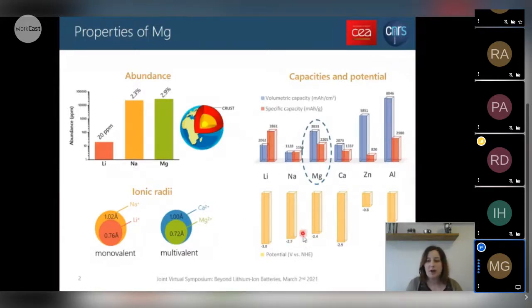Despite a smaller potential of minus 2.4 volts compared to minus 3.0 volts for lithium, magnesium is a great alternative to lithium, as it can exchange 2 electrons instead of 1 for lithium. The main advantage of magnesium is its high abundance in the Earth's crust, which, similar to sodium, could limit the cost of these batteries in comparison to lithium-ion batteries. Magnesium actually presents a higher volumetric capacity than lithium, with a value of around 3,800 milliamp hour per cubic centimeter, in comparison to around 2,000 milliamp hour per cubic centimeter for lithium.